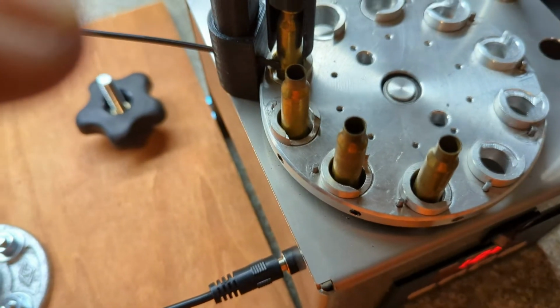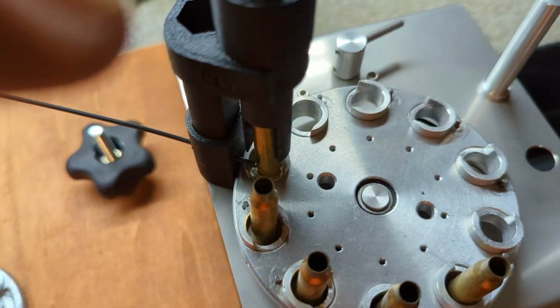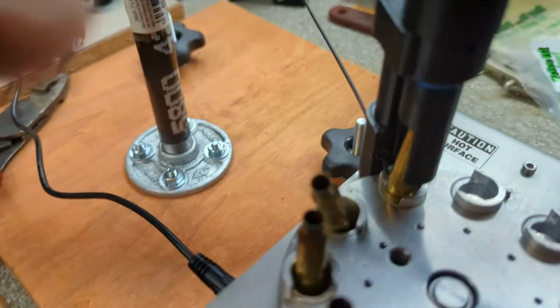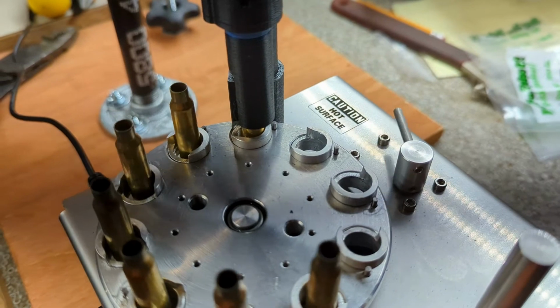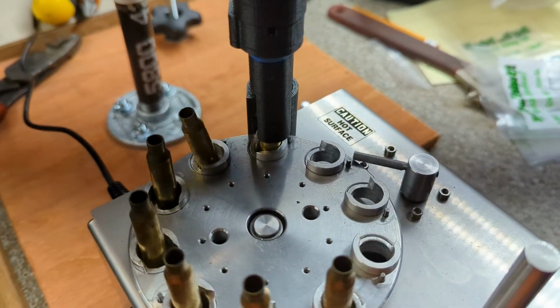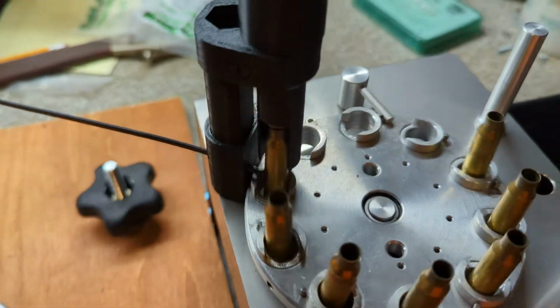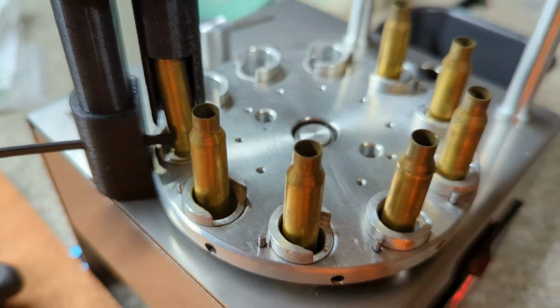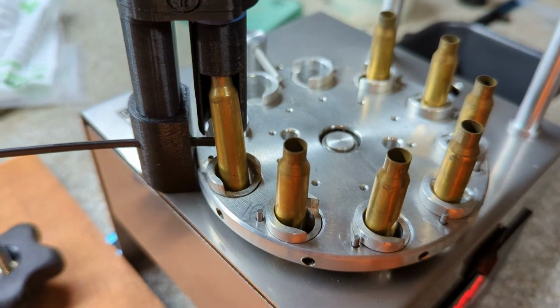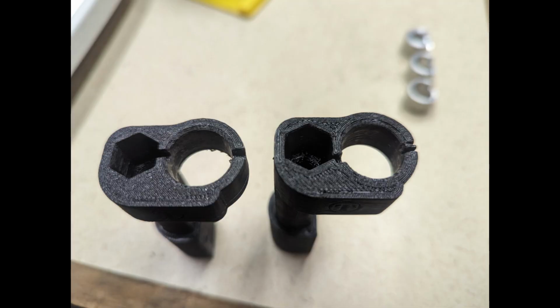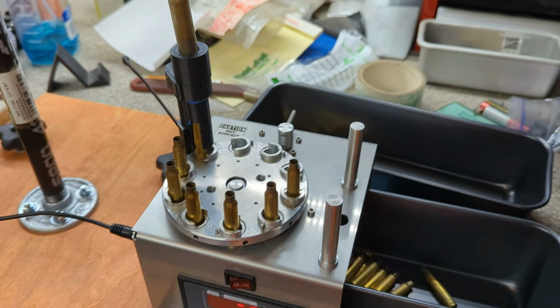The first couple runs on being fed with the case feeder aren't shown here because it worked like trash, jamming and generally being a pain. As I made a few changes, it got better, finally running pretty well other than the jam you see in this short clip right at the end. I changed the orientation of how the drop tube sits in the bracket, clocking it just a few degrees counterclockwise, and tested again, and it worked much better with no failures when I ran about 100 cases through.